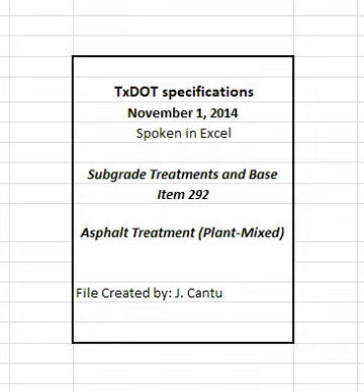Actual in-place density will be determined in accordance with TEX 126E unless otherwise directed. Unless otherwise shown on the plans, obtain required roadway specimens as directed. The engineer will measure air voids in accordance with TEX 207F. When a satisfactory correlation to results obtained in accordance with TEX 126E is shown, other methods of determining in-place compaction may be used. If in-place density is more than 1% below minimum density, cease production immediately.